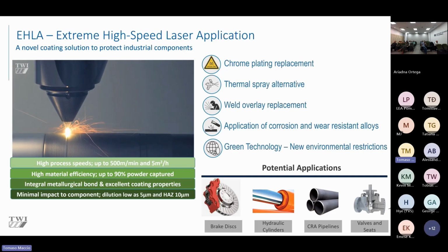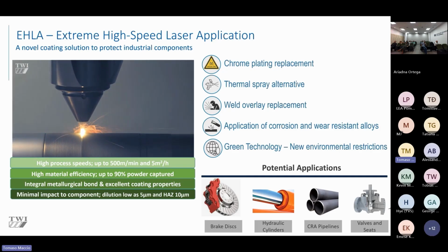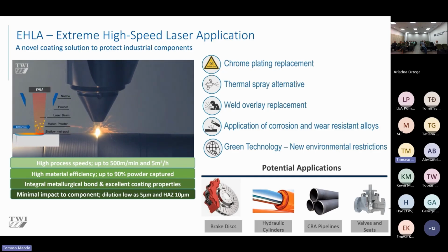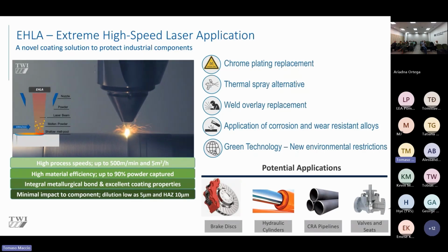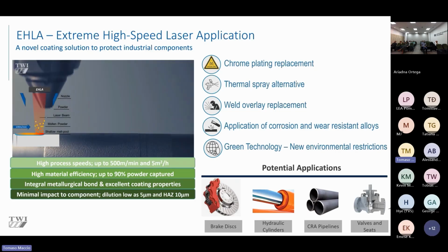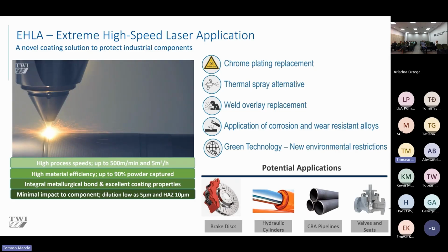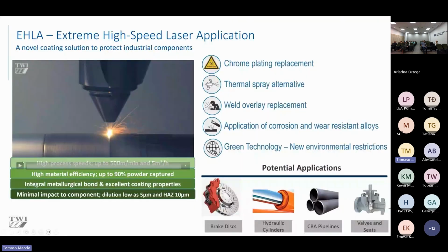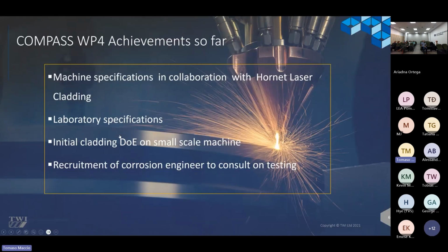Just to give you an idea of the speeds that we can process at, here's another little video, which also gives you an idea of the schematic. The nozzle is the triangular piece. The powder is blowing through there. You can just see the powder in this area, and the laser beam is focused through the cone in the center and deposits onto the substrate. So you're able to do high speed processing. You can see that wasn't sped up. That was in real time, just to give you an idea of the speed of the process.